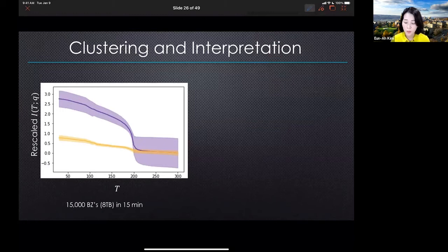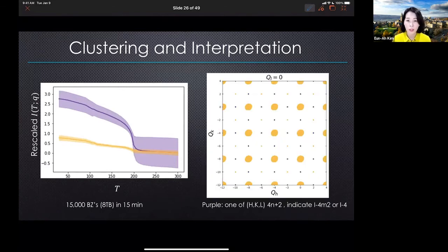Interpretation is really simple, because all you have to do is look at where these cluster assignments came from. This is kind of like looking at a population and sorting it based on tendencies. And now you can look at where they came from to gain insight on whether this is a meaningful result. So to interpret, we look at where these intensities came from, and the colors are matched between the 2 sites. And what you notice is that these purple ones, which had order parameter like onset behavior, came from the reciprocal space point.